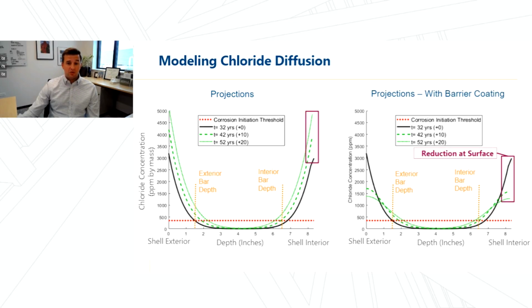First is that we have a reduction in chlorides at the surface. This makes sense. We're no longer adding chlorides, and by diffusion, that higher concentration is going to lessen as those ions try to find their equilibrium point over time. But we also note that we have an increase in chloride concentration at the depth of the reinforcement. So our objective here is not necessarily to limit the total chlorides in the system, but we're concerned with the concentration of chlorides at the depth of the reinforcement.